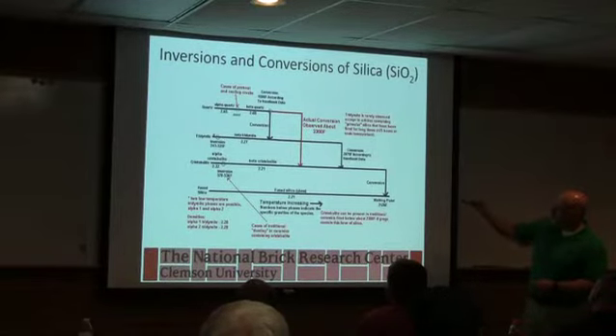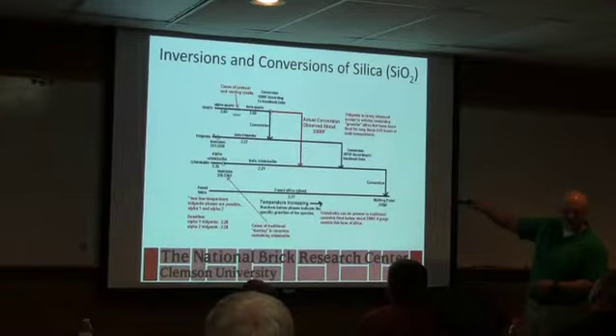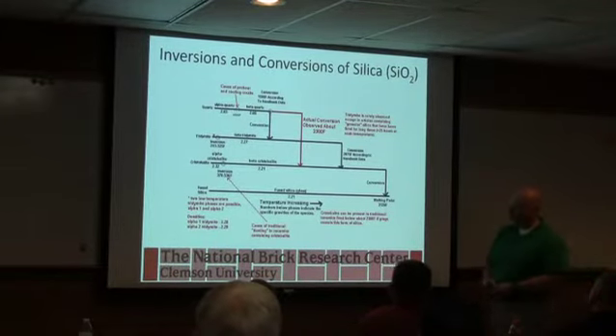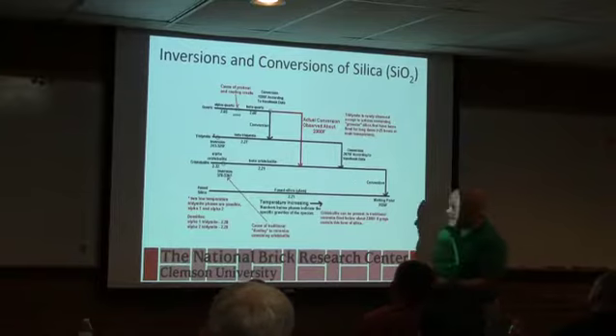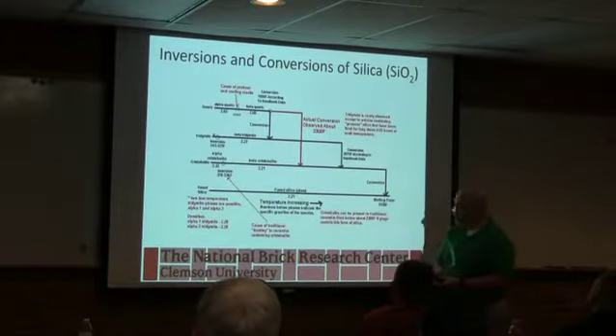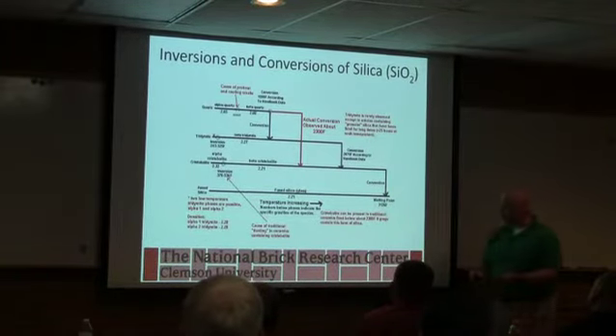So the ones you really see are the alpha to beta quartz, and then in your deck block, this has a low temperature inversion, but this happens to be about the point where the block comes out of the kiln. If there's a lot of cristobalite, that can be a cause of early deterioration in your kiln car deck block. So we see that from time to time.